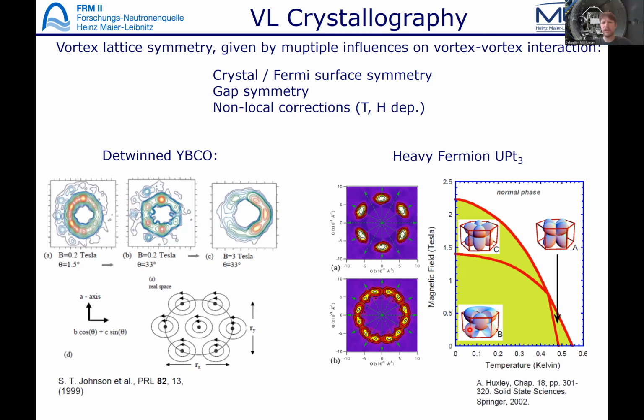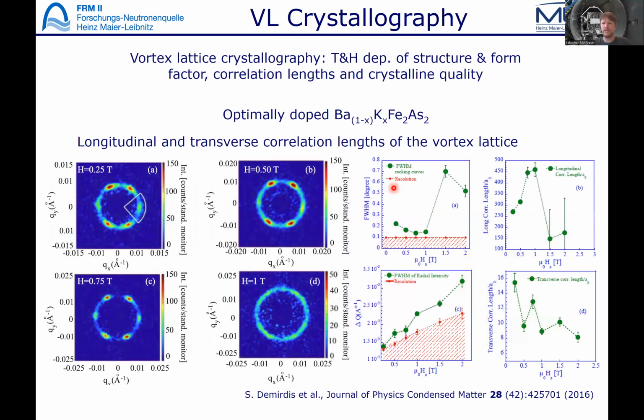So by looking at the symmetry of a vortex lattice, we can distinguish gap symmetry and Fermi surface effects, but we can also look at the temperature and field dependence of the structure factor and the form factor, which is the temperature and field dependence of the penetration depth and the coherence length.